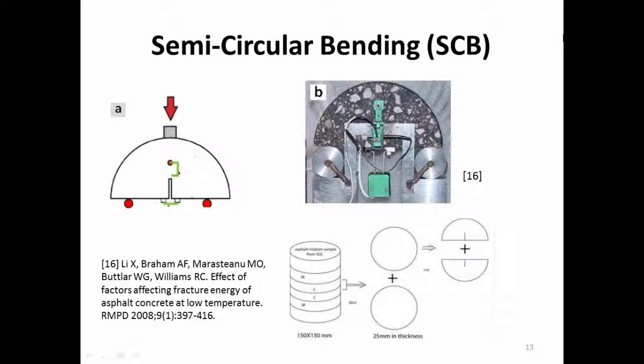But one argument against this specimen is that because of this wedge shape, when you put the load at this point and the crack grows, as it approaches the outer surface, it has a wedge effect. The crack will not grow straight and deviates. So we don't want that, and we want to know what's really happening.